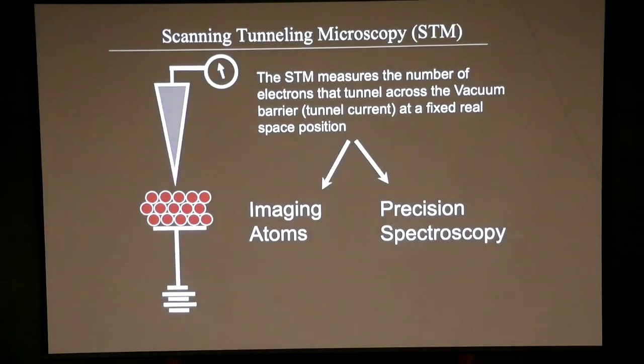So the way the STM works is it's in principle a very simple instrument. You bring a very thin metallic wire to within a few angstroms. So look at this length scale here, a few angstroms of the surface that you want to look at. And then this wire is called the tip. And you turn on a small potential difference between this so-called tip and the sample, and electrons tunnel across the vacuum barrier from the sample to the tip or from the tip to the sample. And we call this current the tunneling current. And this is the one quantity that we measure with the STM, the tunnel current.